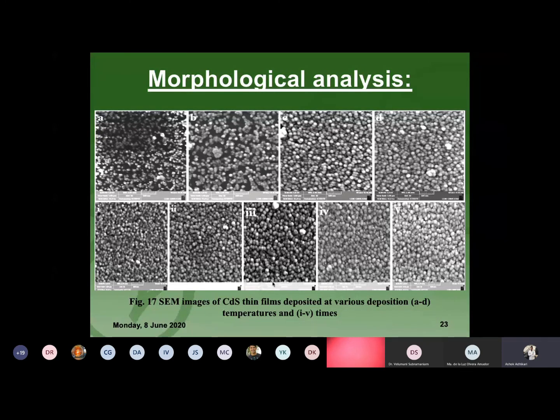But at higher temperature, 80 degrees and 85 degrees, the films are uniform, dense, and homogeneous, with fewer pinholes. Even so, we can still see some pinholes.